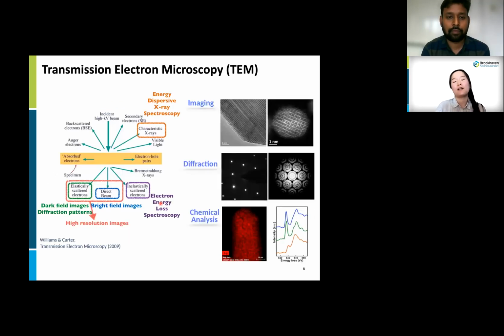When a high energy electron beam hits the sample, tons of signals come out. Using those signals, we can get images and electron diffraction patterns, and we can do chemical analysis with energy dispersive X-ray spectroscopy, like EDX, or electron energy loss spectroscopy, EELS.